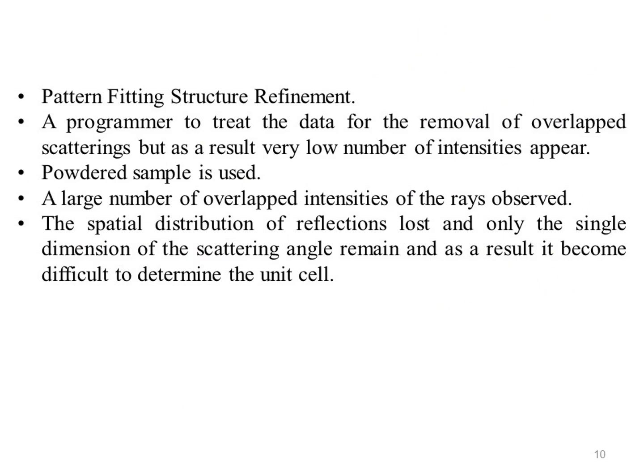Whole pattern fitting structure refinement is now widely accepted to be an exceptionally valuable method for structure analysis of nearly all classes of crystalline materials not available as single crystals. Rietveld refinement is a technique devised by Hugo Rietveld for use in the characterization of crystalline materials. Rietveld refinement is a program to treat the data for the removal of overlapped scatterings, but as a result, a very low number of intensities appear.